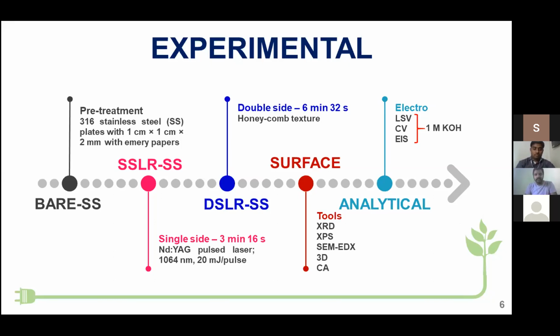These substrates are subjected to surface analysis such as XRD, XPS, SEM, EDX, 3D profilometry, and contact angle. Further, they are evaluated for their electrocatalytic behavior through electroanalytical techniques such as LSV, CV, and EIS in 1 molar KOH solution.